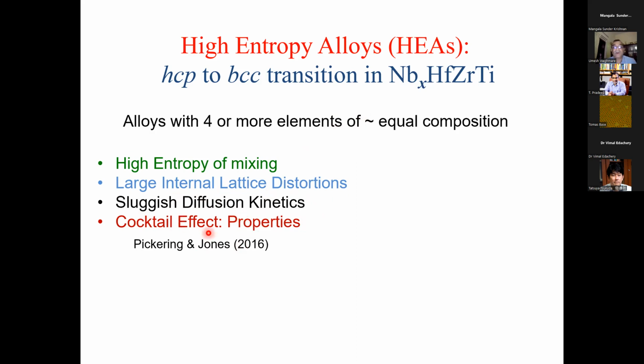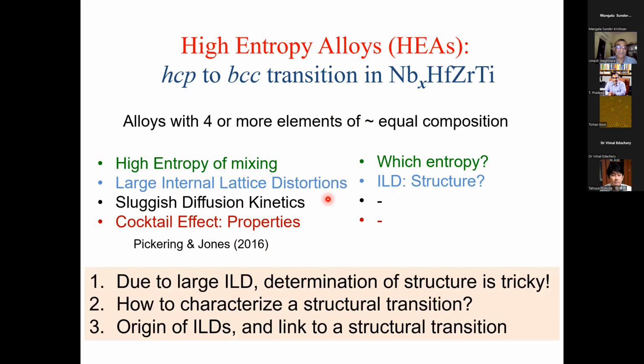And there's something called cocktail effect, which gives rise to amazing mechanical properties of these materials. Of course, what is still open is it's not clear which entropy stabilizes this structure and what is the ILD, which is relevant to the structure. ILD means the internal lattice distortion. Another challenging problem in these systems is that due to large internal lattice distortion, the structure determination is quite tricky. Well, experimentally, it may not be so tricky, but theoretically, you will see it's quite challenging. And how to characterize the structural transition becomes even harder.